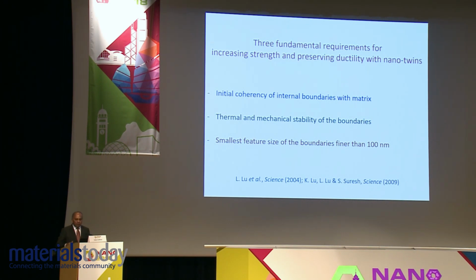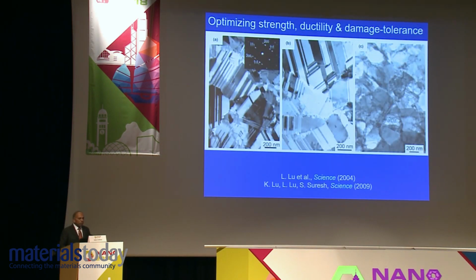And of course, these specimens have been manufactured using techniques where we cannot create very large structures for very large structural components, at least not yet. So in the article in 2009, we looked at the effects of these, and here is an example of a typical microstructure that has been produced. On the left-hand side, this is copper, very finely twinned material, where the twin size is of the order of a few tens of nanometers, a twin spacing, lamellar spacing. The middle one shows something on the order of 70 or 80 nanometers. And on the right-hand side, you see a material of the same grain size, but essentially no pre-existing twins.